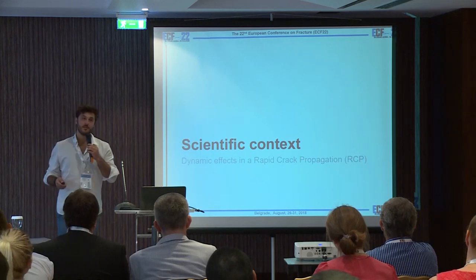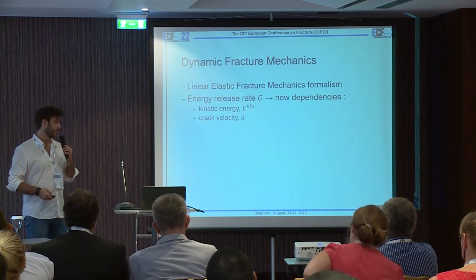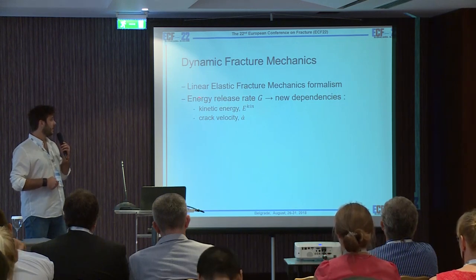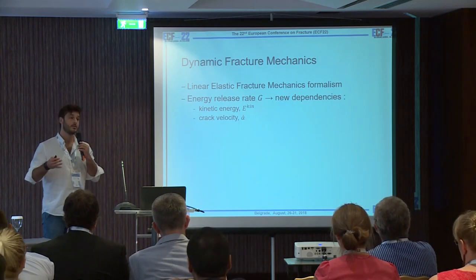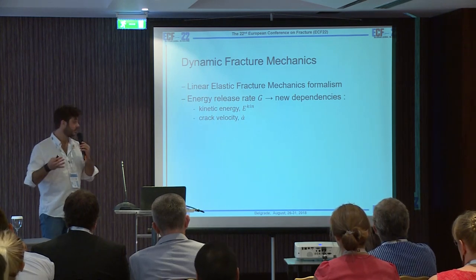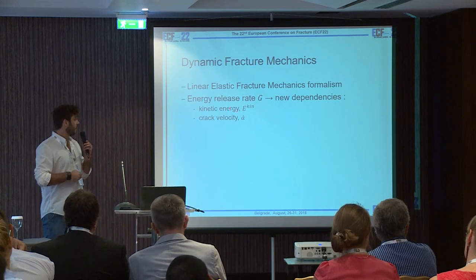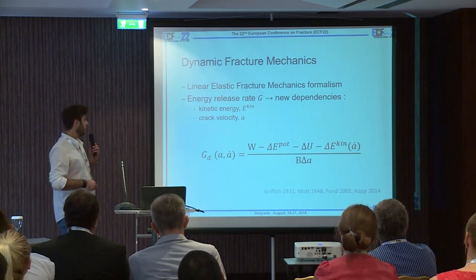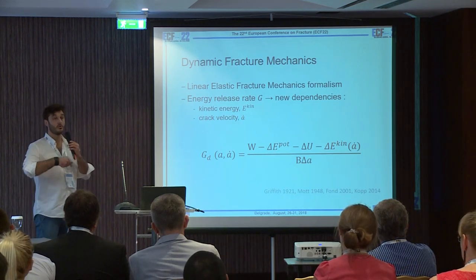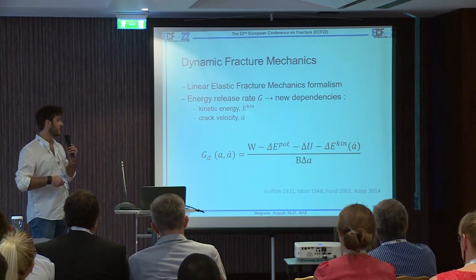Let me first begin with the scientific context related to the dynamic effects when rapid crack propagation occurs. Generally, we are placed in the linear elastic fracture mechanics formalism. Indeed, as the strain rates are relatively high, the behavior remains brittle. Then, the energy release rate, called G, has new dependencies with the kinetic energy and the crack velocity. So, if we perform the classic energy balance during a crack propagation problem, we can see that the kinetic energy appears here and depends on the crack velocity.